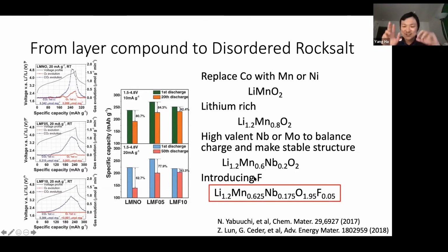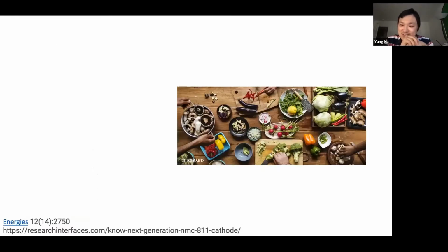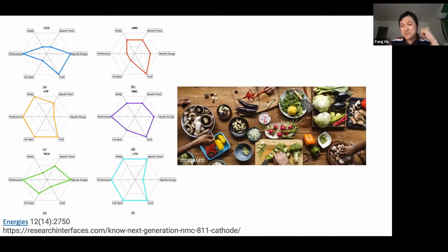And this is what I call a rational design. But material scientists are not always necessarily rational. And sometimes discovering new materials is like cooking. You're trying to have a mix of everything, and hopefully you end up with something good. And when I say good here, I mean a high dimensional metric. In this literature, good is considered to be a long lifespan, great performance, nice safety, high power and high energy density. And of course, you have to take cost into consideration. So you can see it's really hard to satisfy every criterion. And so people start from some simple components like lithium cobalt oxide and lithium manganese oxide, and then they start to move to NMC, which is nickel, manganese, cobalt, and NCA, which is nickel, cobalt, aluminum.